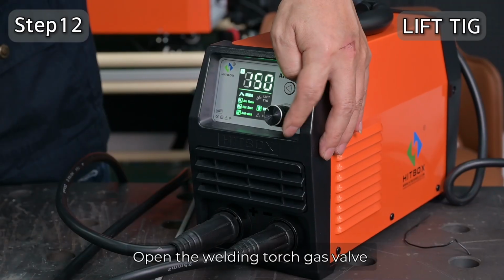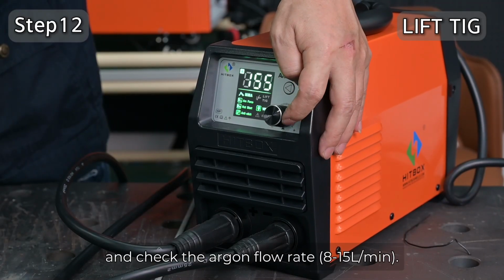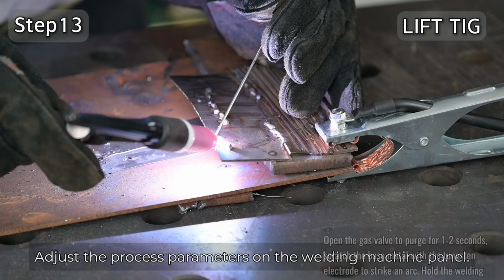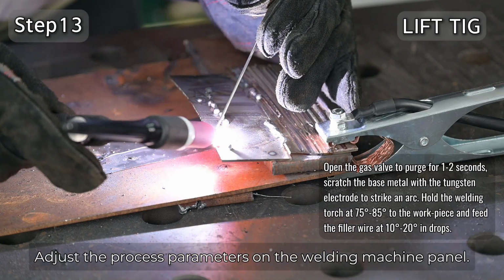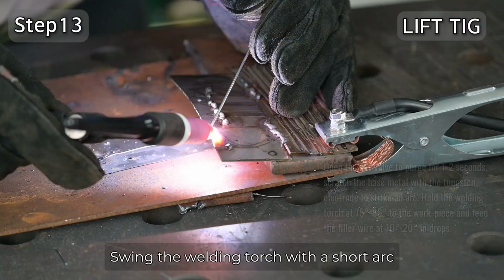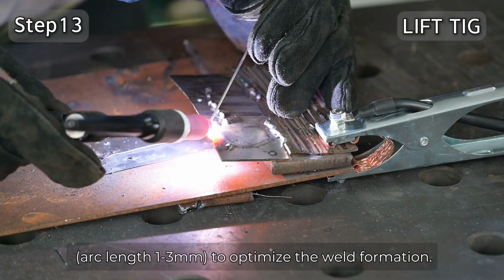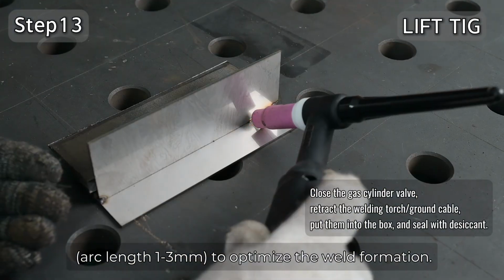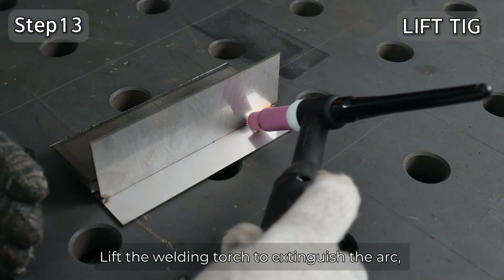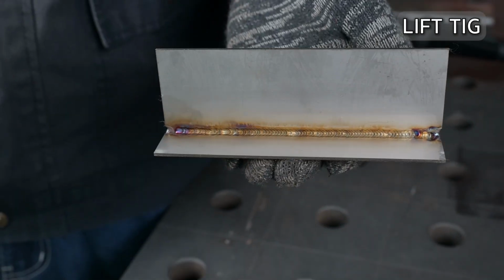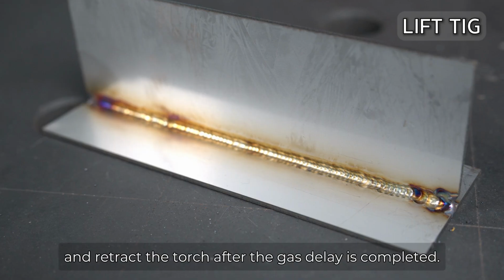Open the welding torch gas valve and check the argon flow rate, 8 to 15 liters per minute. Adjust the process parameters on the welding machine panel. Swing the welding torch with a short arc length 1 to 3 millimeters, to optimize the weld formation. Lift the welding torch to extinguish the arc, and retract the torch after the gas delay is completed.